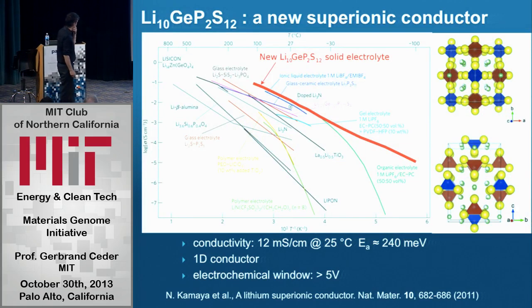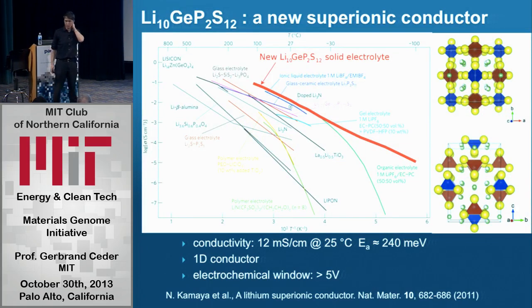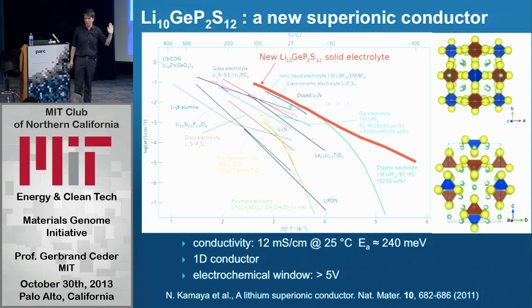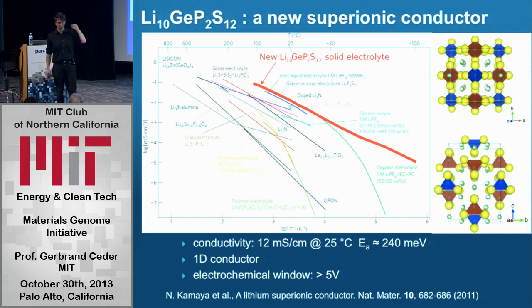But 2 years ago, a few groups in Japan proved us wrong. Kanno et al., working with Toyota, showed that this material, which is referred to as LGPS, a lithium germanium thiophosphate compound, has really high conductivity for lithium ions. At room temperature, it is as good a conductor as the liquid electrolytes we use today, which is amazing. This is a solid through which the ions go as fast as through a liquid.